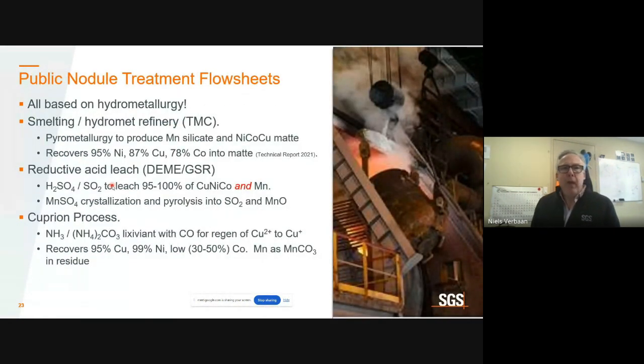Okay, so trying to summarize these 3 flow sheets here, they're all based on hydrometallurgy. The smelting hydromet refinery flow sheet by TMC uses pyrometallurgy to produce a manganese silicate. So it's got a good outlet for manganese and then produces the matte. Recovery is somewhat suppressed. The reductive acid leach uses sulfuric acid and SO2 gas and leaches all 4 metals, but uses internal recycling via manganese sulfate crystallization and pyrolysis back into SO2 and MnO.